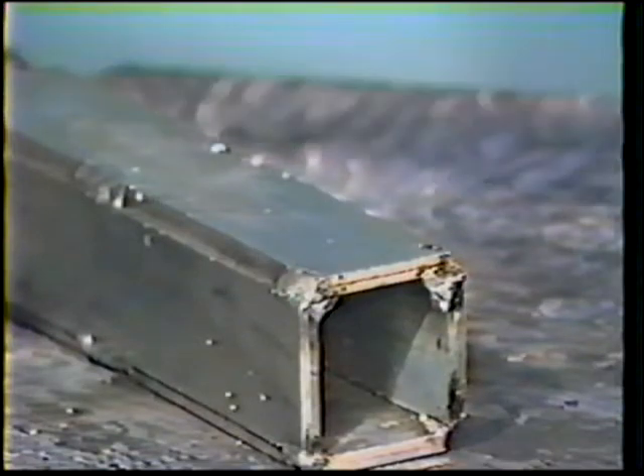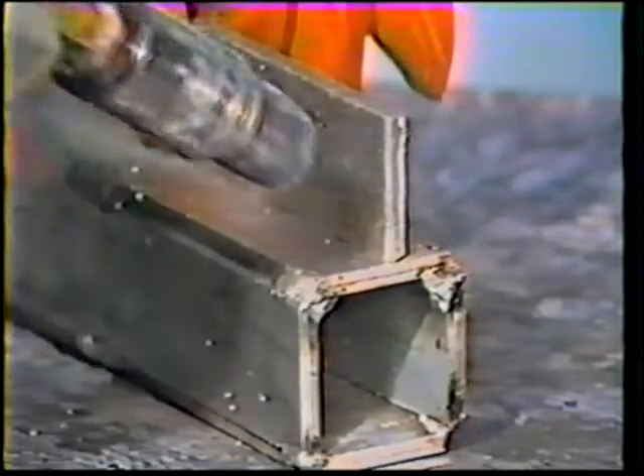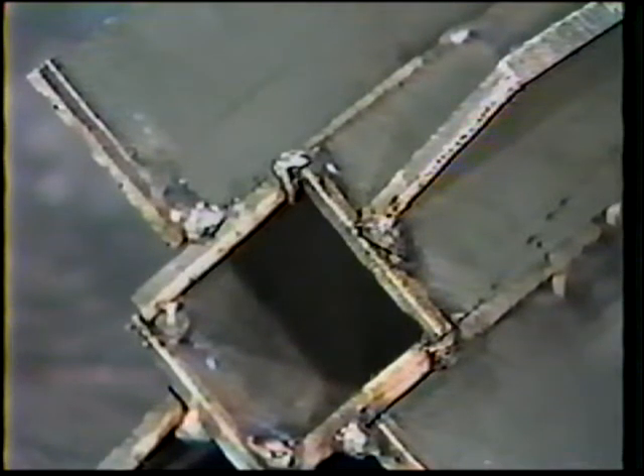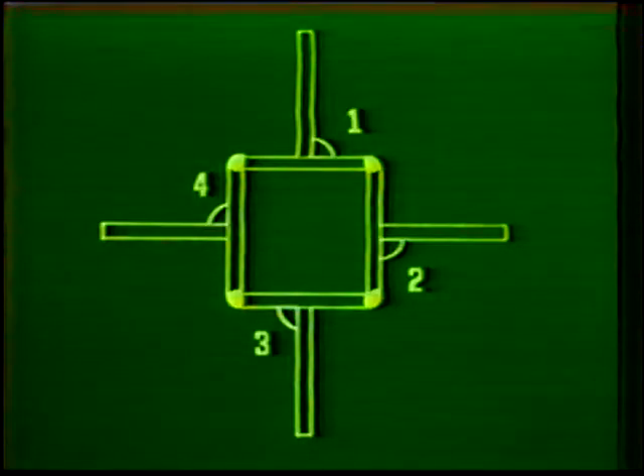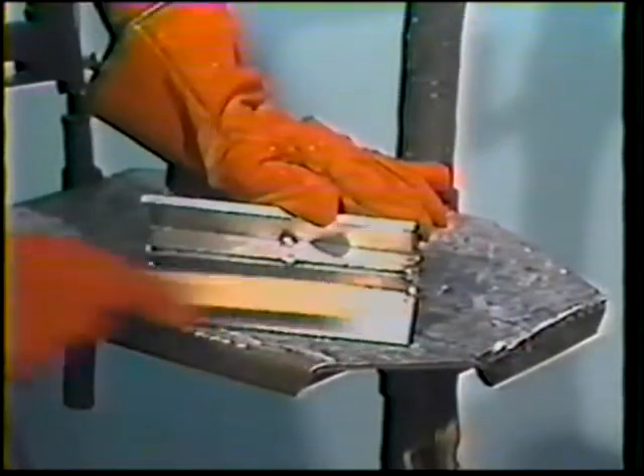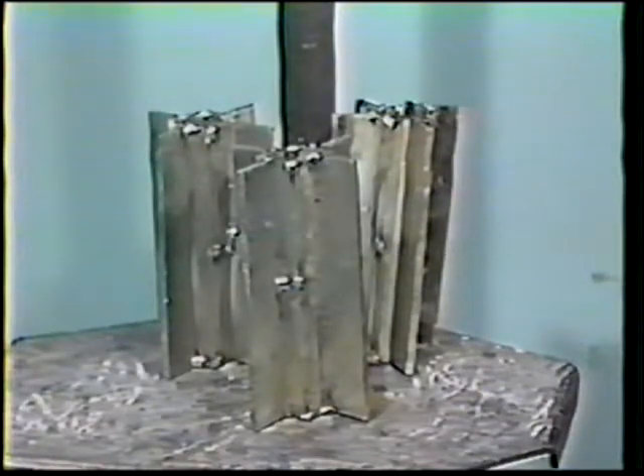Now, tack weld the 4 remaining plates perpendicular to the sides of the assembled box to form the T-joints. The plates are tacked at each end to fasten them to the box. However, the back side of each plate should receive an extra tack weld in the middle to prevent expansion of the joint or cracking from heat buildup during welding. While the joints are still hot from tack welding, thoroughly brush them clean to remove surface oxides. Assemble 3 complete workpieces before beginning to weld, so that the pieces can be alternated and allowed to cool thoroughly between passes.